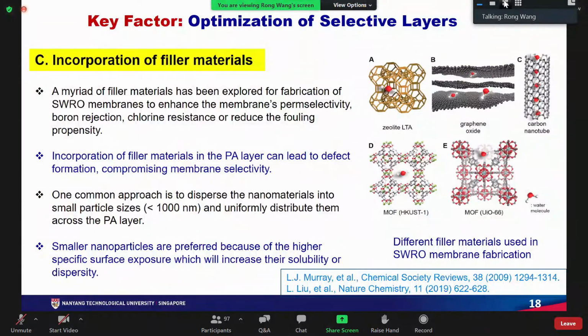But the issue is that the incorporation of the filler material in the polyamide layer can lead to defect formation. Therefore, it will compromise the membrane selectivity. Another challenging issue is that when we scale up the fabrication, how to avoid the defect formation. This is the critical issue.